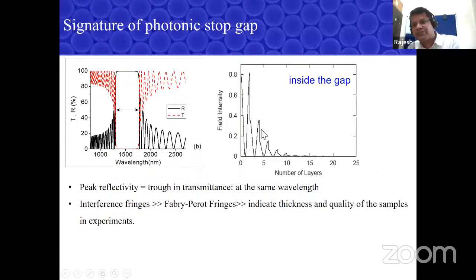It penetrates into the system because it's an interference process: it goes, reflects back, and interferes constructively. So this is a kind of signature of a photonic band gap if you measure it. In all this analysis and work, we keep absorption at 0 in the system. So the absence of transmission is not absorption; rather, it is a strong reflection of the light at the designed wavelength.